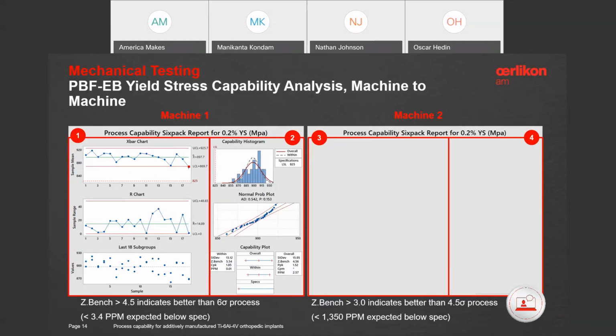So with the control charts and normal probability plot in good shape, we move on, draw histograms of our process data, throw in the specification limits for ASTM F2924, and calculate our CPKs. If we do this, we'll discover a couple things. First of all, for a manufacturing process considered capable, typically a CPK of at least 1.33 is desired. Our CPK values are always greater than that. As a matter of fact, the Z-score, which is another way of expressing process capability, exceeds 4.5. And the projected scrap rate is less than 3.4 parts per million, which is equivalent to a 6 sigma process.